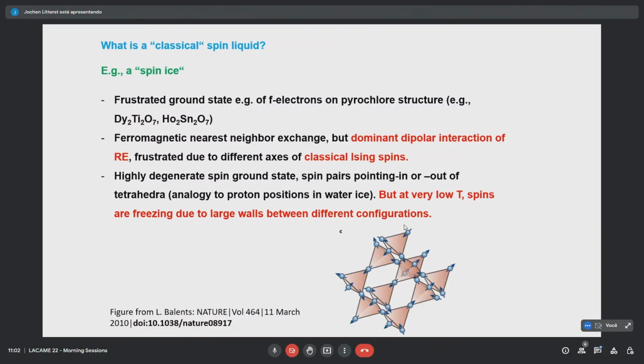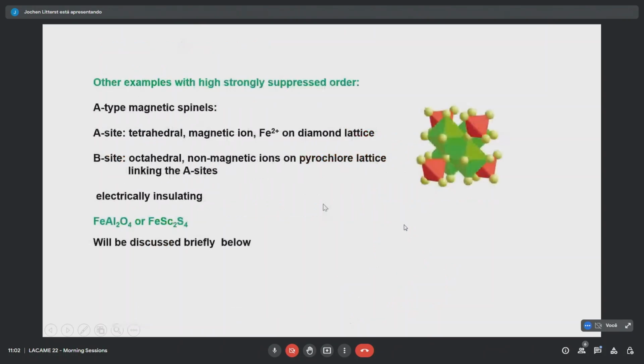Now, I had said before, at low temperature the spins should not freeze and they should stay fluctuating down to T equals 0. That's not the case here. The reason is you have large spins, and these large spins have large barriers in fluctuating between the different configurations. So finally, if you go down to low temperature, it will freeze. So it's not a true spin liquid in that definition as we had defined before.